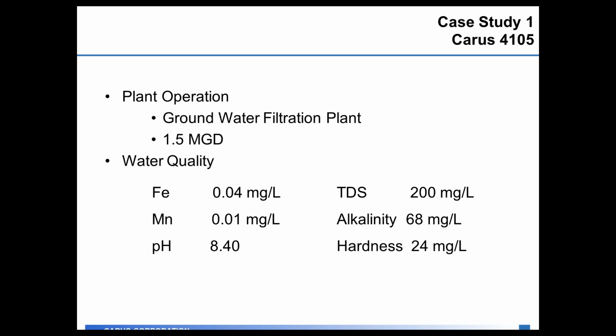The plant operation, it was a groundwater filtration plant, 1.5 MGD, and their water quality shows that there wasn't really any iron in the water leaving the plant at 0.04 milligrams per liter, so that would tell you the red water complaints were coming from corrosion in the distribution system because there wasn't iron in the source water. Manganese was 0.01 milligrams per liter, so below the 0.05 secondary maximum contaminant level. The pH they were adjusting to was 8.4. Their hardness in this water was only 24 milligrams per liter, so very low on the hardness scale. Alkalinity down at 68 milligrams per liter.